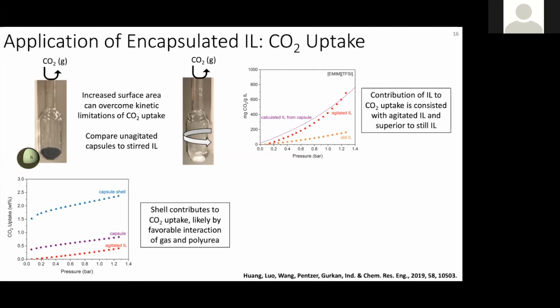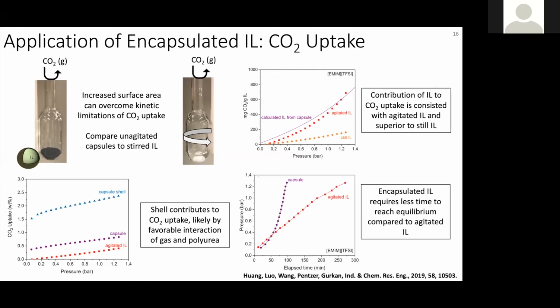And so while this was promising, we also found that the time it took to reach equilibrium for CO2 uptake was significantly less, or it happened more rapidly for the capsules than it would for the agitated ionic liquid. And so we think there's essentially plasticization of the polymer shell with the core material, and that facilitates mass transport.